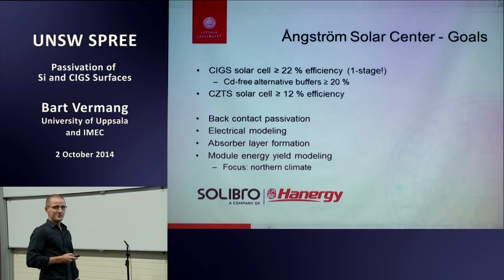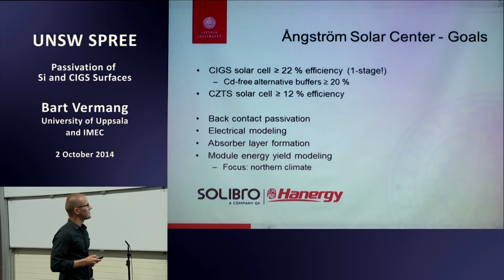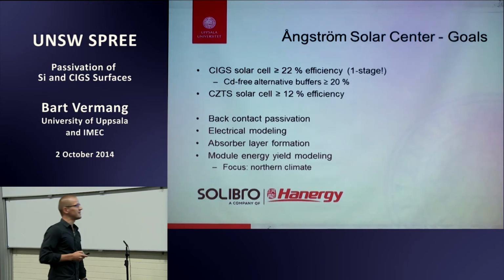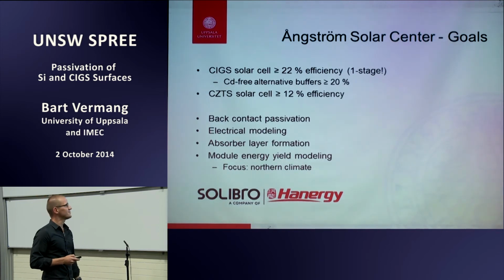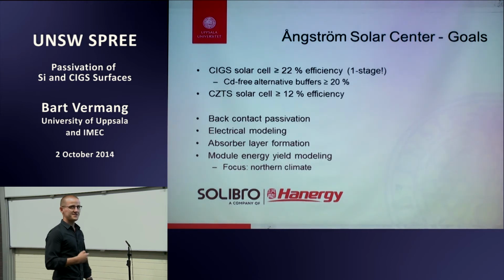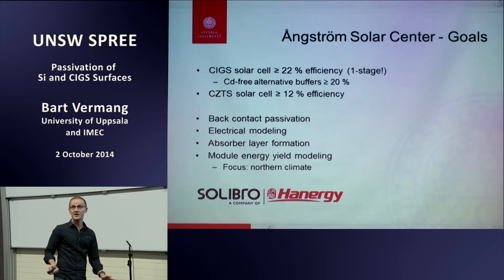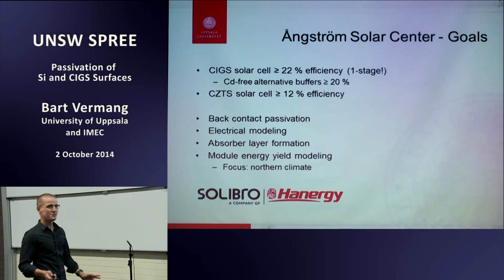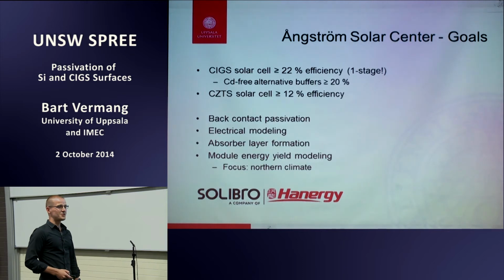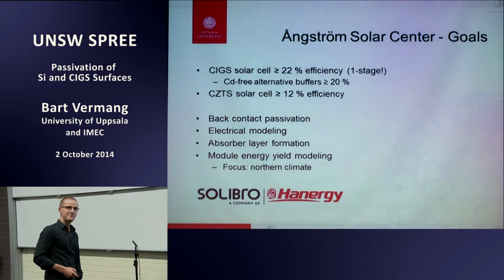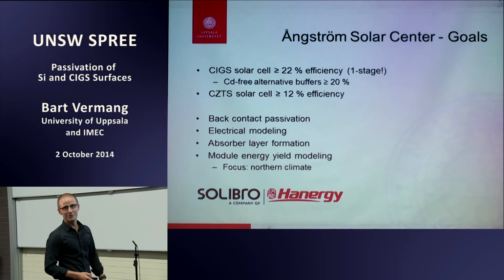So last week at the EU PV-SEC there was an announcement by ZSW that they reached 21.7% efficiency on CIGS. That's a top record efficiency. However, as an ex-silicon person, it's only 0.5 square centimeter. So what does it really mean? I don't know. As well, they're always comparing it to multicrystalline, and the best multicrystalline is 20.4, also 0.5 square centimeter, but except in industry, no research labs are still optimizing multicrystalline silicon solar cells, so they shouldn't compare in my opinion, but still.